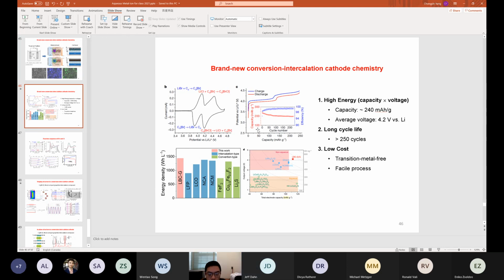It's not purely about the window anymore, because for the cathode side, it's only lower than 4.5. So 21 molar and 28 molar both work well. For the anode side, because we actually protect the graphite, there's also not much difference between 21 molar and 28 molar.